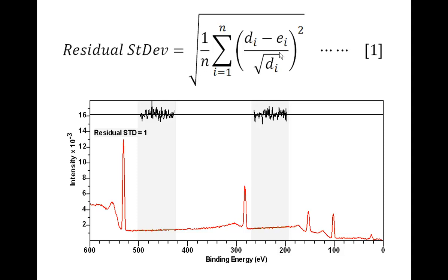Because we know that the uncertainty in each data bin is expected to be the square root of the counts per bin, this is a measure of the difference we ought to see between the data and the curve. So the difference of the data from the curve and the square root of the counts per bin ought to be very close in value to each other.